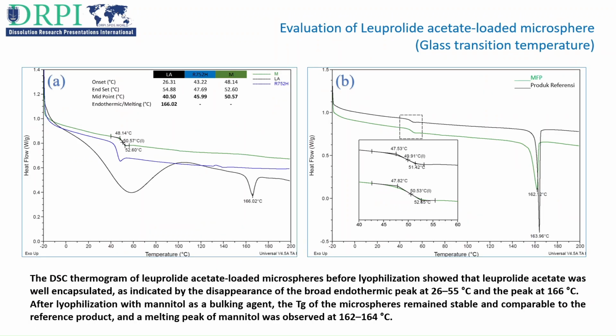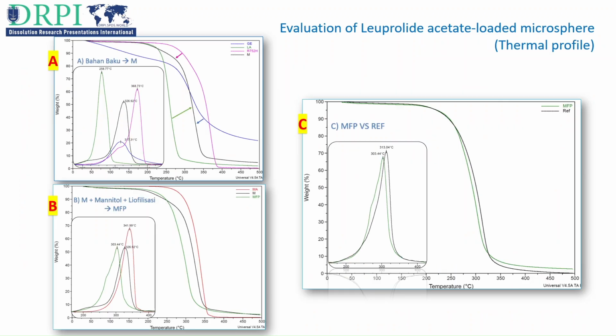The DSC thermograms of Leuprolide loaded microspheres before lyophilization, as you can see in figure A, showed a successful encapsulation indicated by the disappearance of broad endothermic peaks between 26 and 55 degrees Celsius and the sharp peak at 166 degrees Celsius. After lyophilization, as you can see in figure B, with mannitol as a bulking agent, the glass transition of the microspheres remained unchanged and comparable to the reference product, with a mannitol melting peak observed at 162 to 164 degrees Celsius.